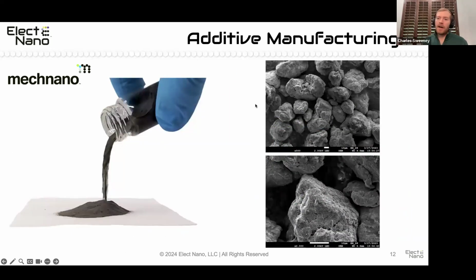We've also developed SLS powders at MechNano, so the ability to put our nanotube technology on top of the powders, so you can improve the properties of the system. You get ESD at very low loading levels of carbon nanotubes in this case. That's a really neat technology for powder bed processing. There are several companies that are scaling that technology now, and we commercially offer SLS resins that have our discrete nanotubes built into them.